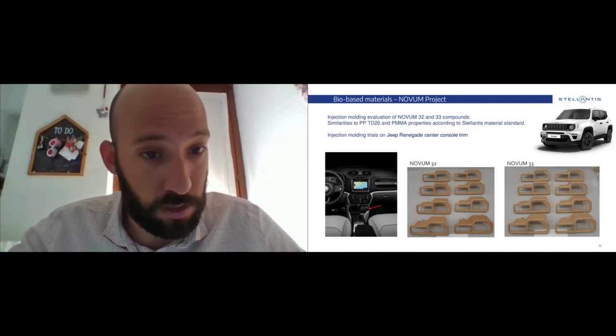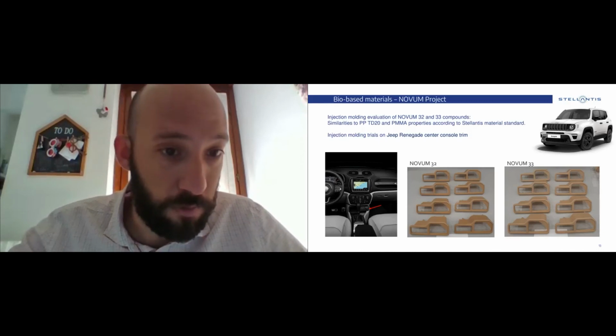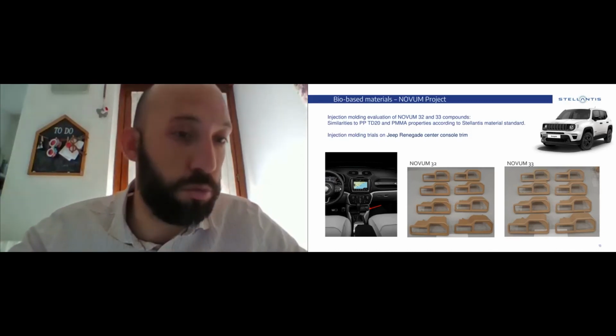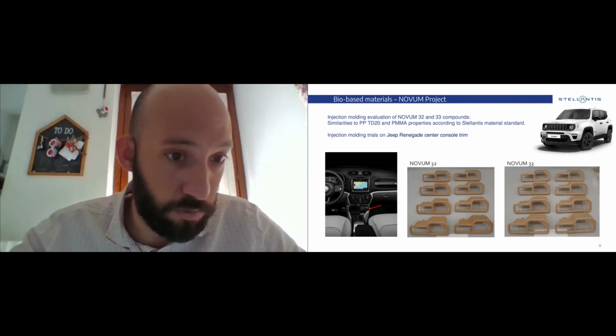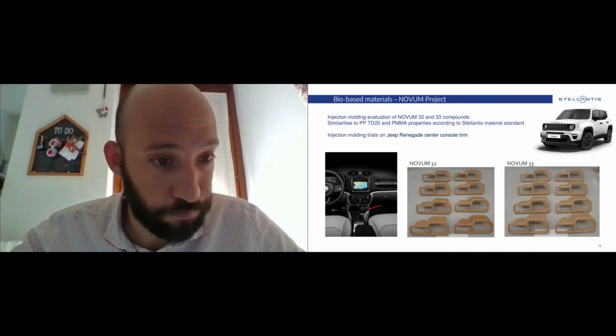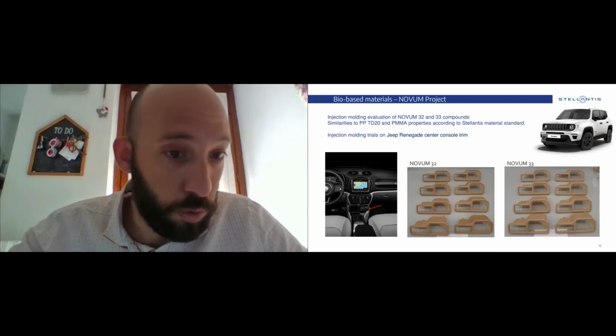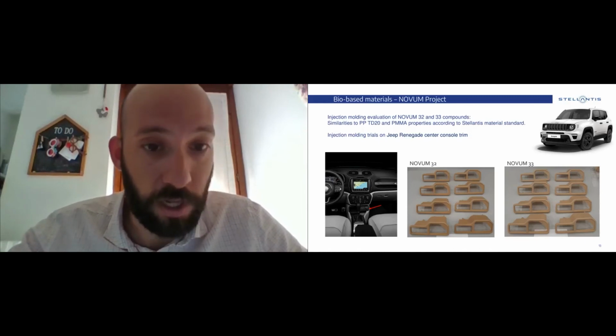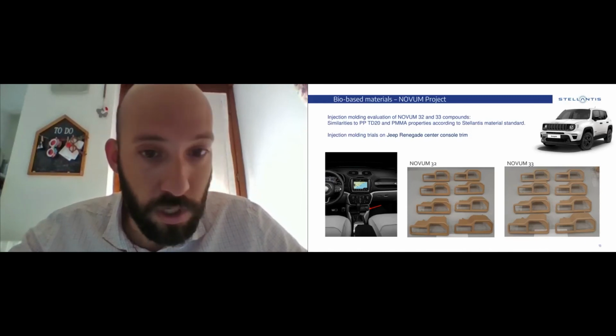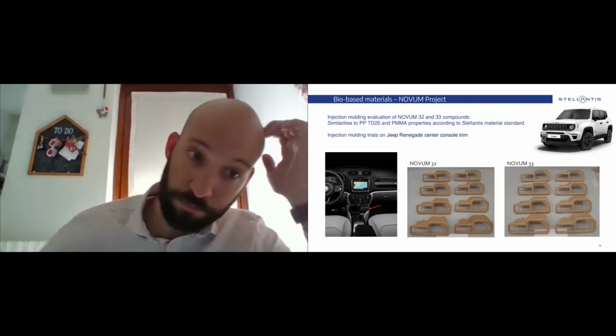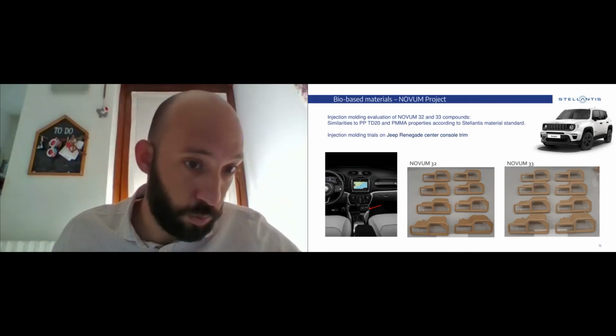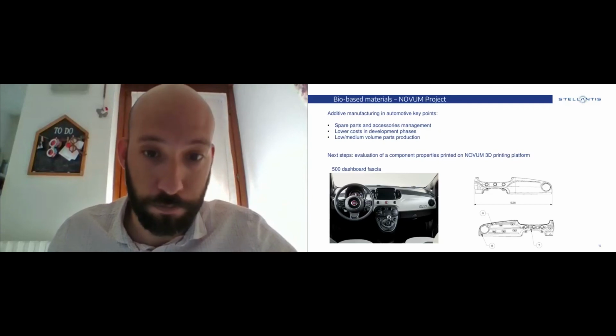We saw that they show similar properties to polypropylene talc, and for this reason, we tried to mold it on an existing mold of the Jeep Renegade center console. And we have really good results because we see a really good processability in the mold and also good aesthetics. As you can see in the photo, we inject really good parts.